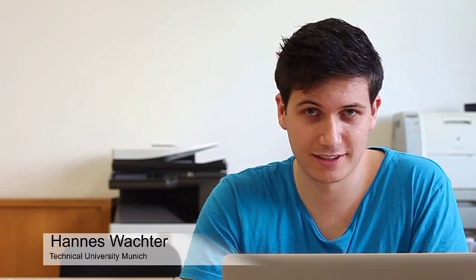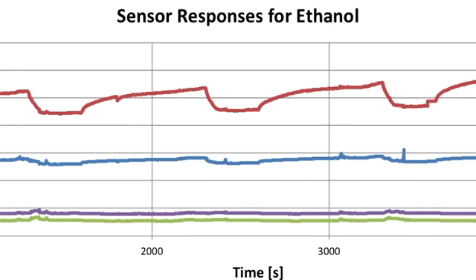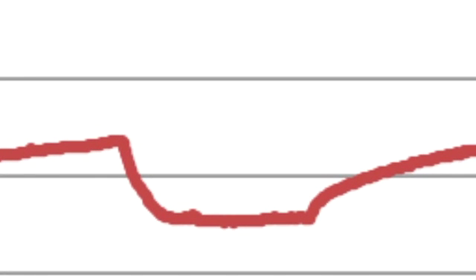If we now look at the response of the four sensors, the resistance decreases as the palladium nanoparticle size increases. During the measurement we can see strong oscillations of the four sensors which are on the one hand due to the temporal changes caused by the active recovery and on the other hand the responses to the different concentrations of ethanol and ammonia.